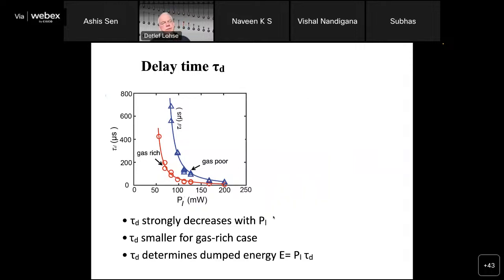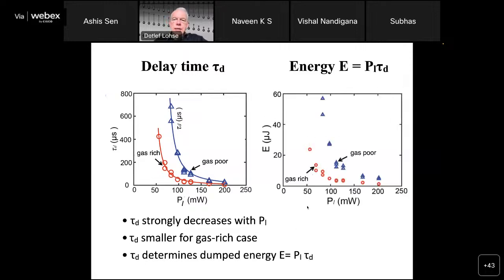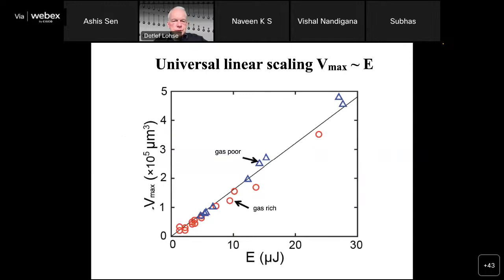And what in fact is relevant for the growth of this bubble is not the laser power, but the energy which is dumped into the system. This is the laser power times the delay time, because here things can accumulate. The energy around the bubble can accumulate. So the relevant parameter is the laser power times the delay time. Here I calculate this energy pumped into the system versus the power, taking this delay time into consideration. And when I now plot this energy dumped into the system versus the volume of the bubble, I get this beautiful linear relation.